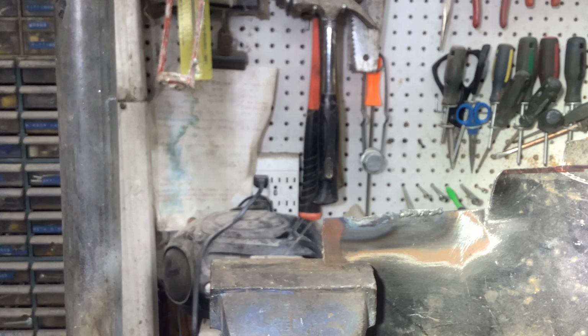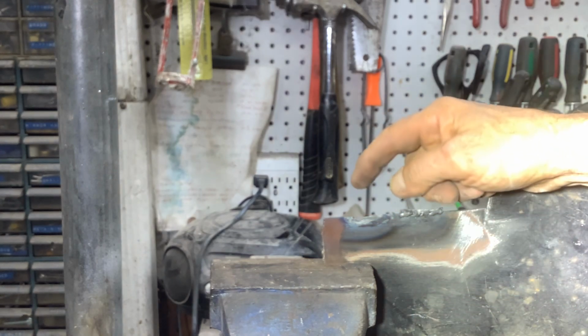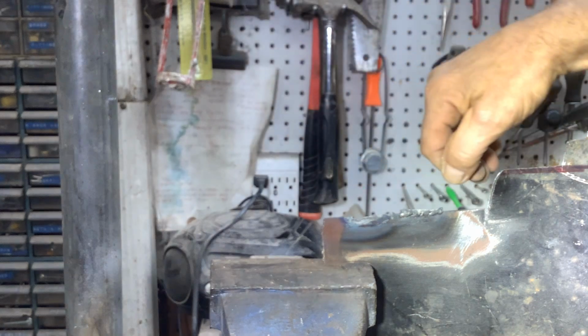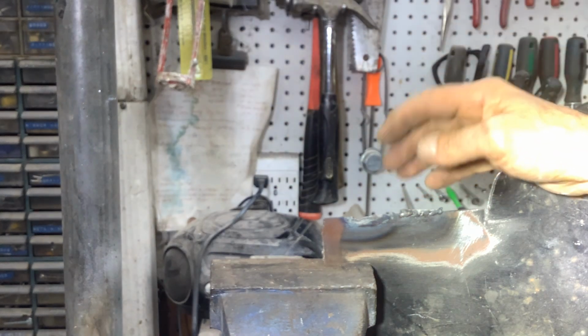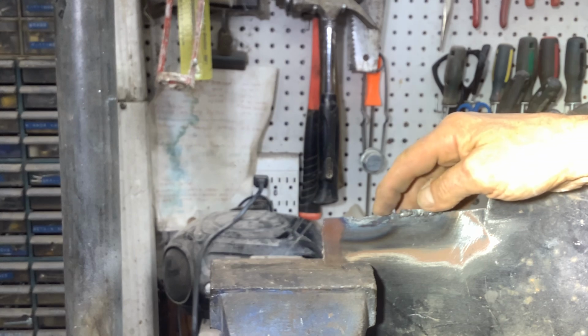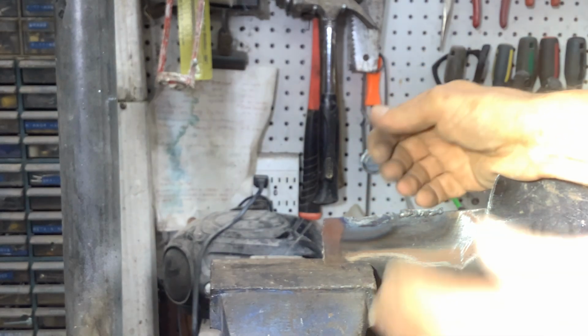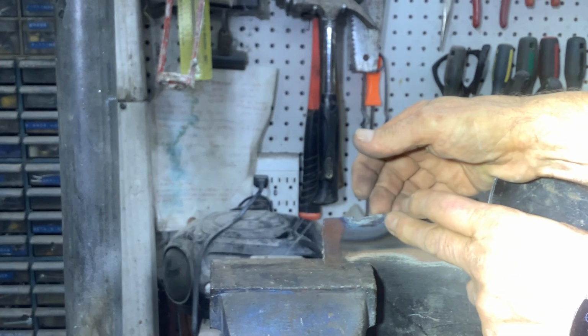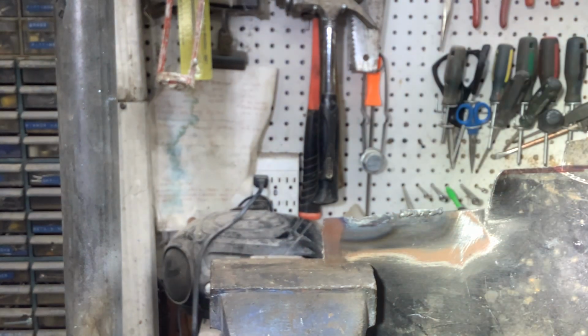If we didn't anneal our teeth on properly, when the saw went down and it was cutting, the teeth would tear off. If it was done properly, the weld was welded properly from both sides, forged, all the air taken out of the welds, and then annealed, that is the only way the teeth stayed on. If the welding process was flawed, a bad weld annealed will not stay on. If you got a good weld and it's not annealed, it won't stay on. So everything has to be done right. The welding process has to be good, and a weld should be annealed.